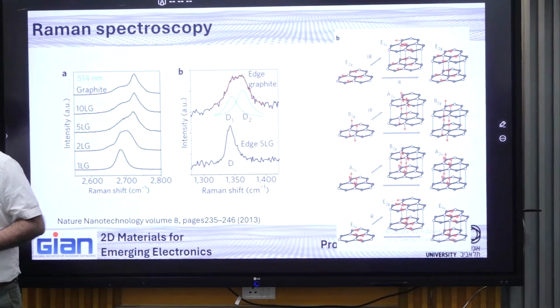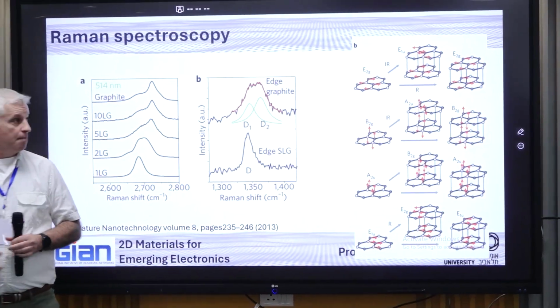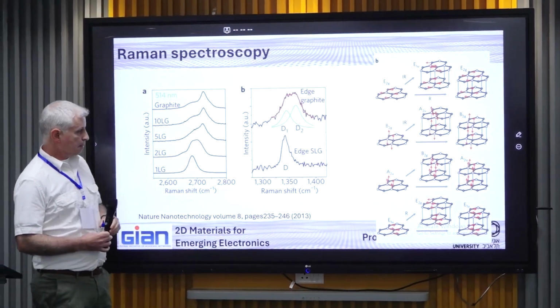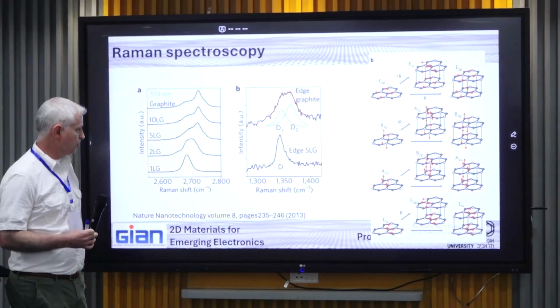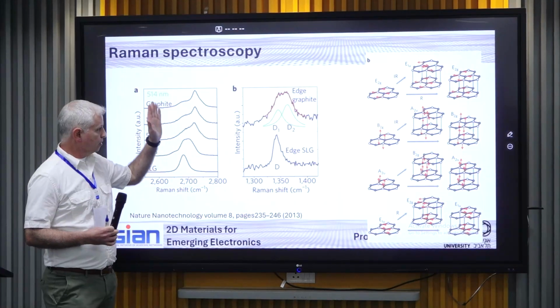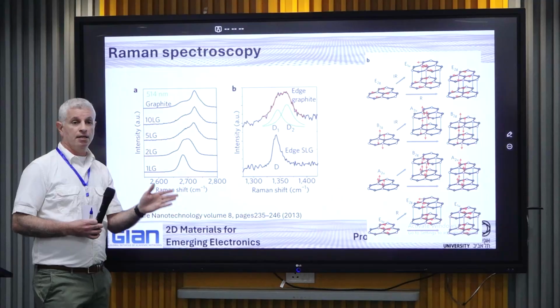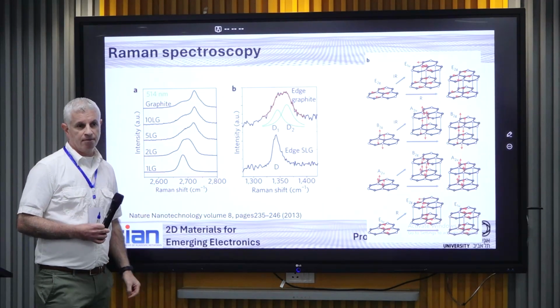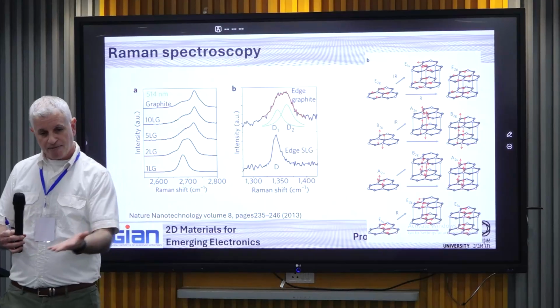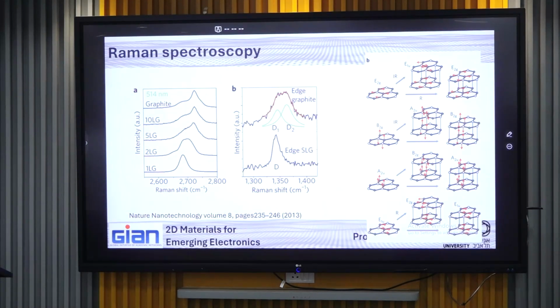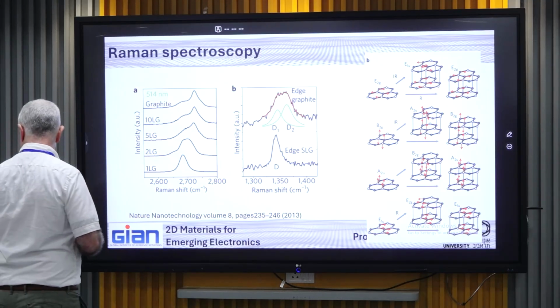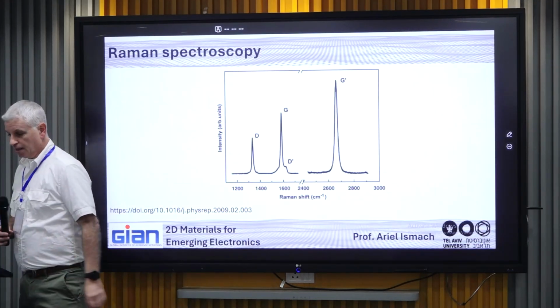Therefore, as you can see, Raman in graphene systems, in special, but also in some of the other 2D materials, is very good in order to identify and prove that you have a single layer. Even if you came from the optical microscope with something that you believe, according to the contrast, is a single layer, you put it now in the Raman, and you should get a very specific Raman spectrum. Okay? And so, yeah, which is this spectrum.